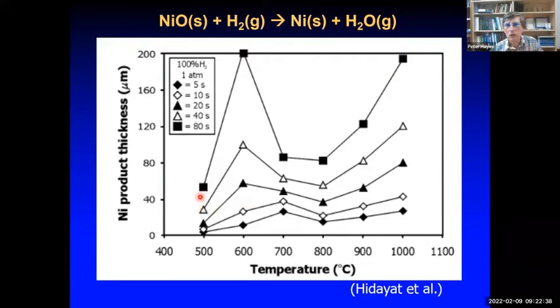But again, we don't see anything that obeys the Arrhenius equation here. As we increase the temperature, the rate increases quite dramatically from 500 to 600 degrees centigrade. But then after that, it actually drops off. 700, 800, 900. And there we're back to that situation where the rate at 500 or 600 is the same as 1000. So we have some other additional evidence to show that this happens in the CO2 system as well as the hydrogen steam system.